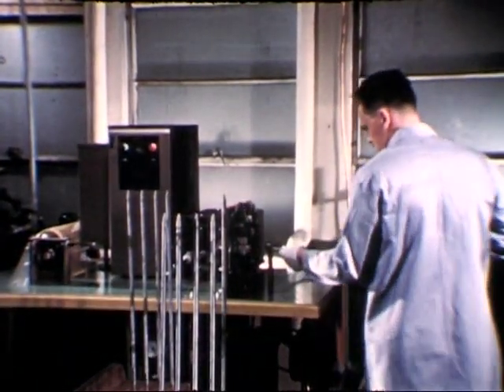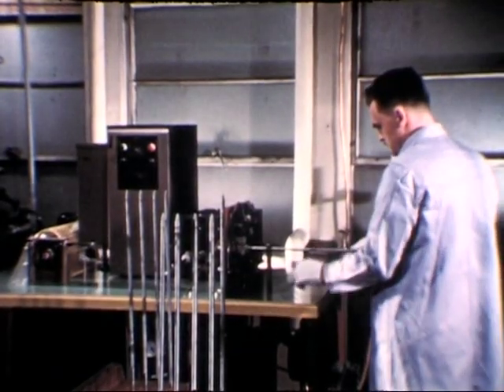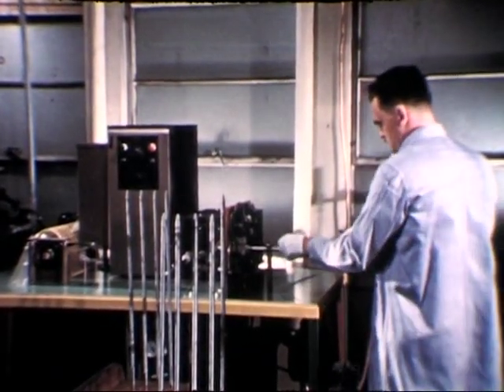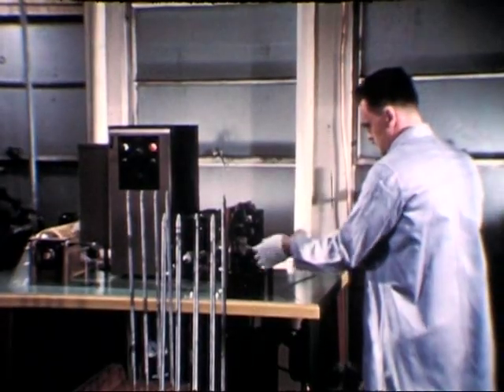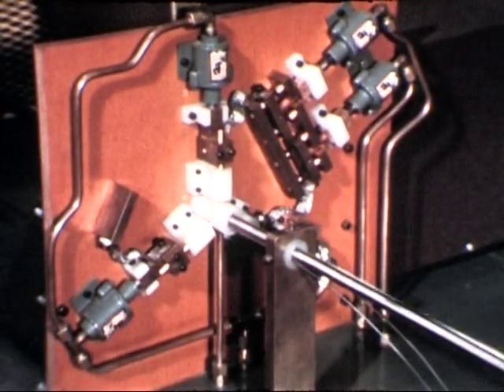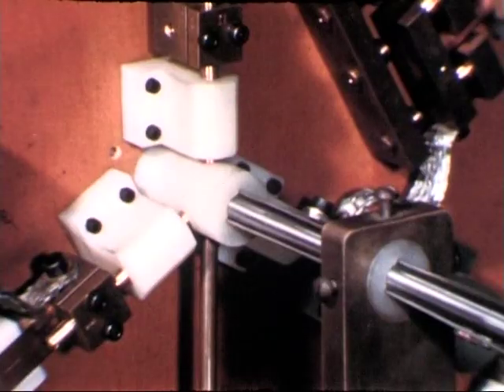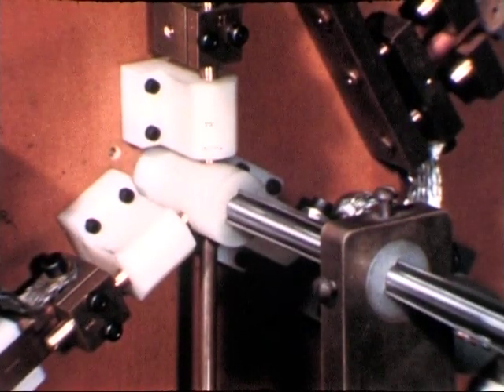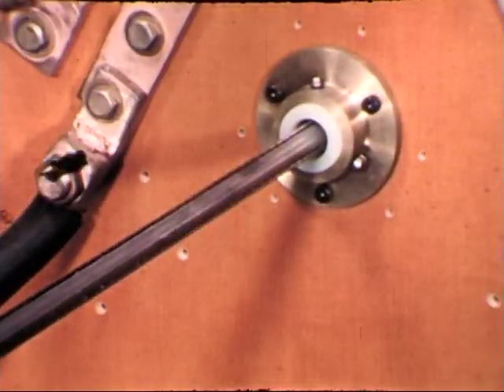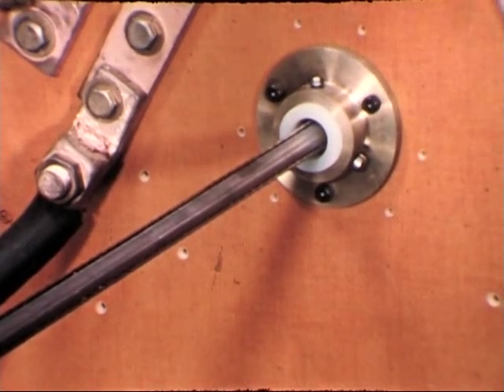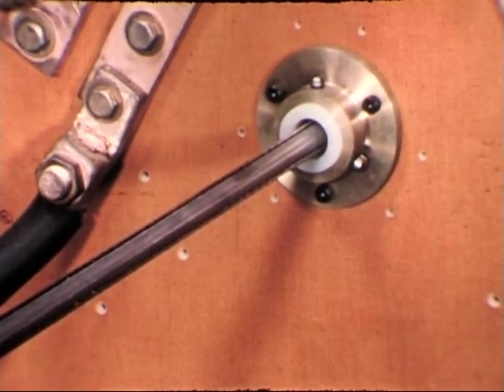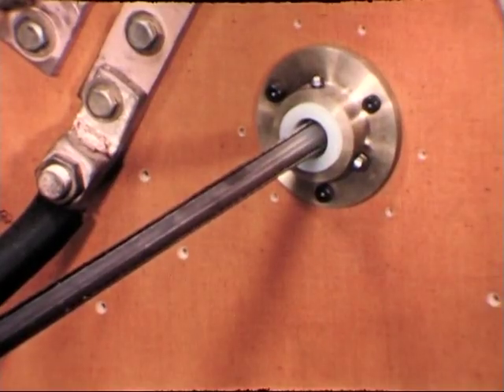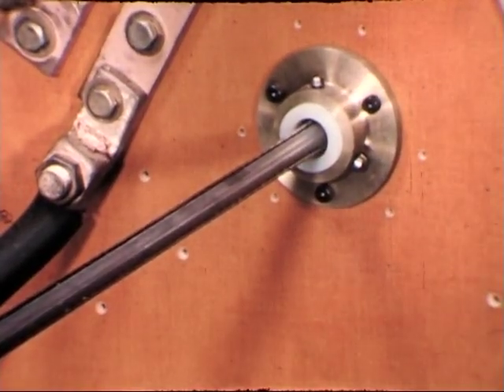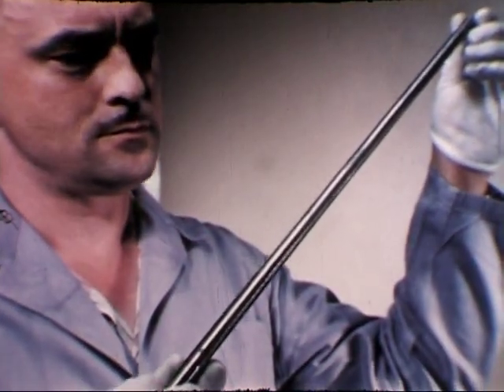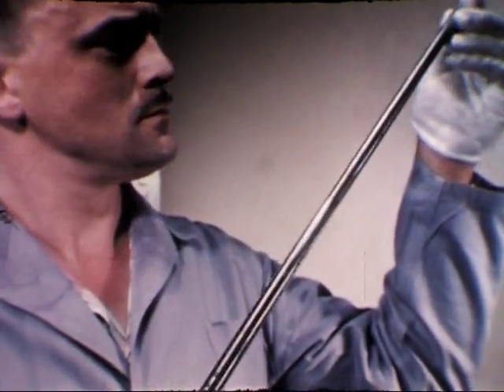Zirconium ribs are spot welded to rods ground to their finished diameter. These will provide accurate spacing of the tightly clustered rods in their final geometry. The welding operation is performed automatically on a specially designed condenser discharge type spot welder. Welds are placed at 1/4 inch intervals along each of the 3 ribs, a total of 240 welds per rod. Machining operations complete the fuel and blanket rod fabrication.